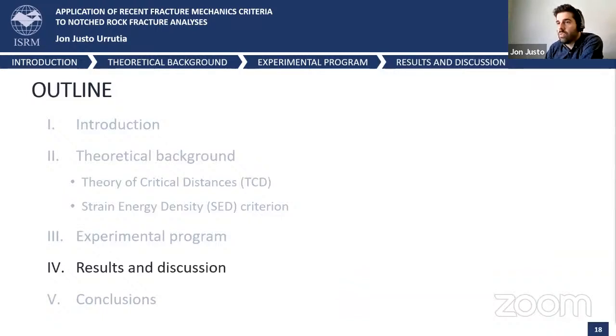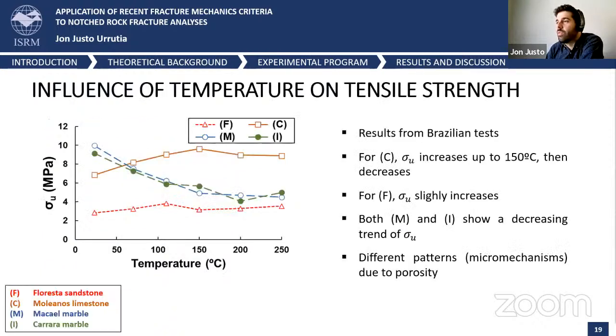So let's move now to the results and discussion, which is probably the most interesting part for you. This first slide shows the variation of the tensile strength with temperature. I have assigned a different color to each rock for a better visualization of the results. It can be observed that the tensile strength of the Moleanos limestone, for example, increases up to 150 Celsius degrees, and then slightly decreases. The Floresta sandstone also shows a slight increasing trend with temperature. However, both marbles present a reduction of the tensile strength from the onset of the heating process.